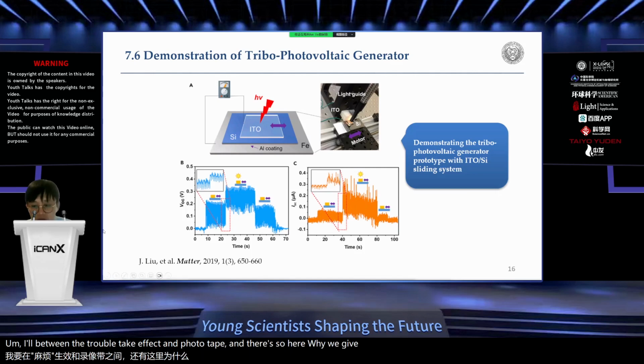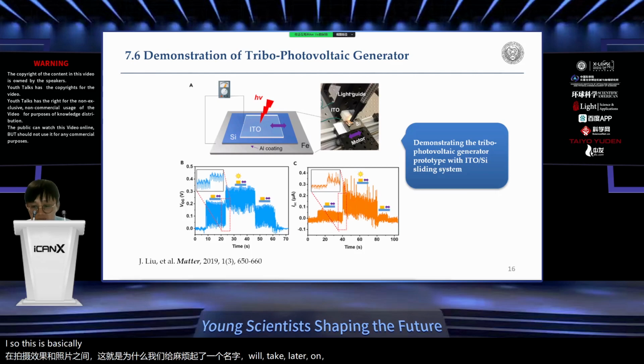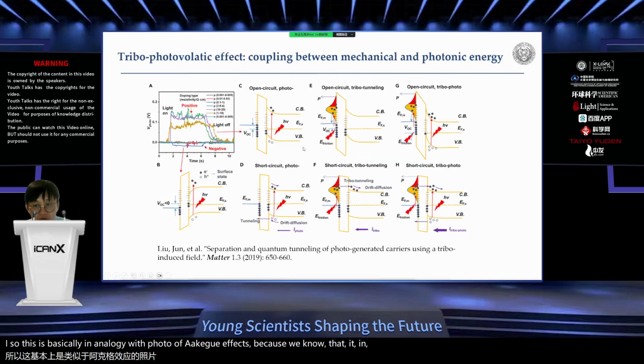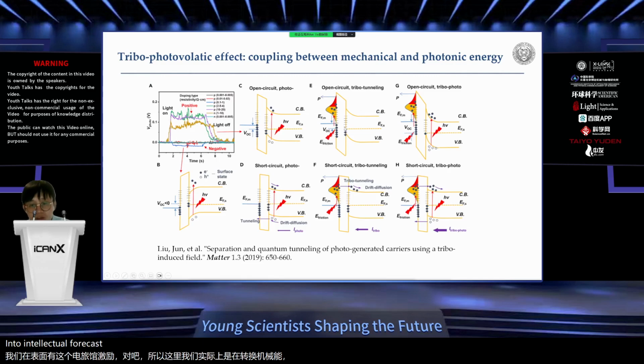And then here, why we gave it the name tribovoltaic later on is basically in analogy with the photovoltaic effect, because we know that in photovoltaic systems, the electron hole pairs are generated by irradiation from photons, right, in a semiconductor. This corresponds to the case right here, for example. And if you have triboelectric DC generation, you can see that instead of generating electron hole pairs inside the depletion layer, we have this electron hole pair excitation right at the surface, right? So here we're actually converting mechanical energy into electron hole pairs, right? So that's why we say that it is very similar to the photovoltaic effect, and then we can also call this phenomenon the tribovoltaic effect, right? And then when you have this mechanical stimulation and irradiation together, you might be able to excite the electron hole pairs simultaneously with mechanical energy and photonic energy.